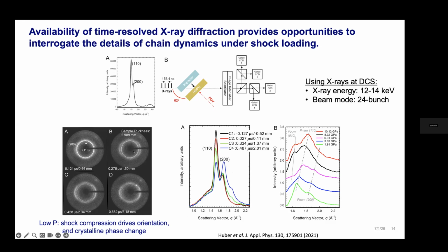And then if you look just at the images on the detector, what you can see is that there is evidence of orientation, because you see that intensity change along the x-axis here. That indicates that shock compression is driving orientation of the polymers, specifically of the crystalline domains under shock, which is interesting because they're highly orienting to the shock direction, but it's also driving this phase change. So again, we see the growth of this monoclinic structure and the disappearance of the orthorhombic structure as we shock to higher pressures. So that was very satisfying.